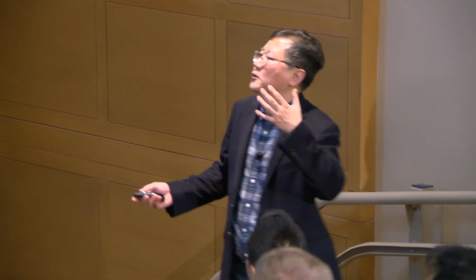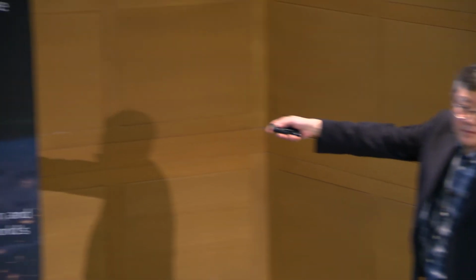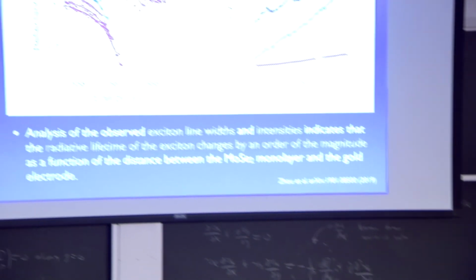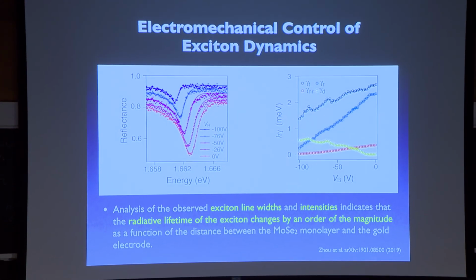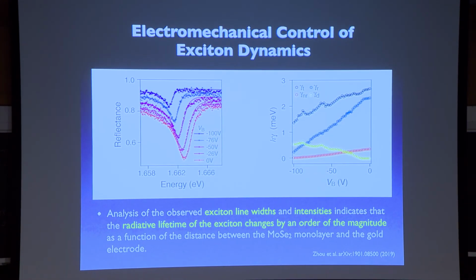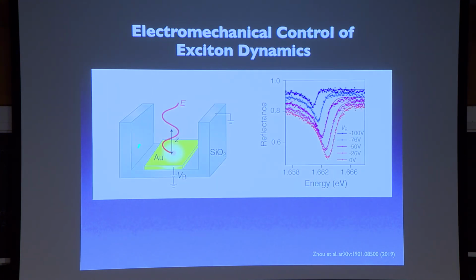Yes, great question, and thanks for pointing it out. It turns out that we actually had to do a lot of control experiments to separate it out. The shift in the line positions is related to the strain that you are inducing into the layer by changing the distance. Essentially, by pulling the tent, you are generating a strain, and that shifts the position. But that does not change the line width. We can independently do that without the mirror, and you can actually prove that. Basically, all you have to do is shine the laser light where there's no mirror, and then see the position. Yes, that's a great question.